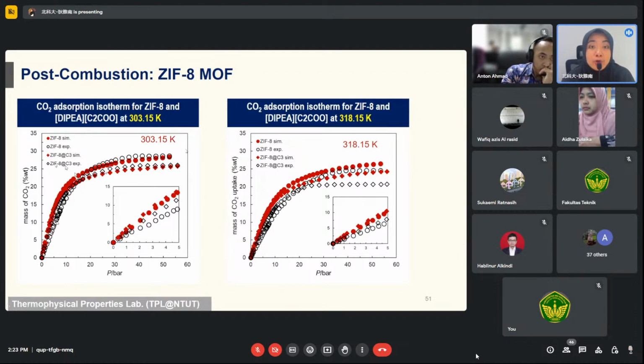This is good for flue gas application. But for high pressure, 20 bar up to 55 or 56 bar, the pristine ZIF-8 is much better. So that's why there is a cross point here, around 16 bar. So what are the solid circle and the solid diamond here? It's simulation. We use RASPA software.